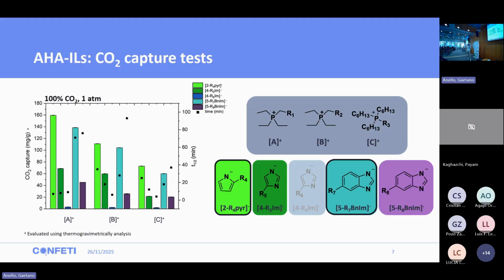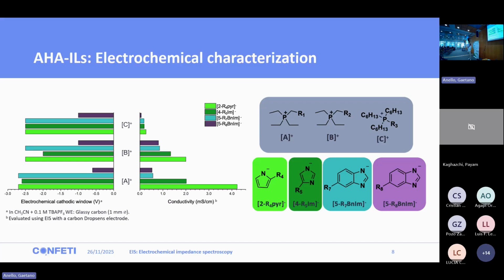Beyond the CO2 capture, we also did electrochemical characterization, because in the end we want to use these as electrodes or electrolytes. So we measured the electrochemical cathodic window using cyclic voltammetry and the conductivity using electrochemical impedance spectroscopy. In the case of the conductivity, the smaller the cation, the higher the conductivity. And in the case of the electrochemical cathodic window, most of the ionic liquids show an adequate cathodic stability from -2 to -2.7 volts. That is enough for the CO2 reduction, except these ones, the purple ones, that show a smaller electrochemical window. This was due to the presence of a nitro group in the structure, and we are observing the reduction of this nitro group.